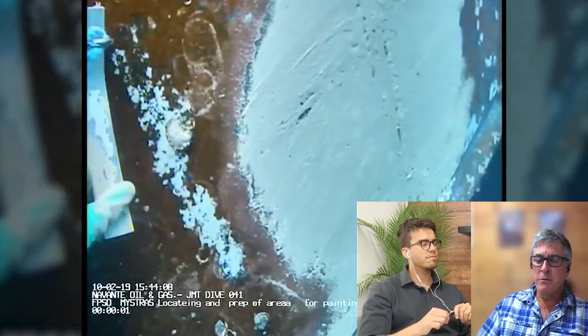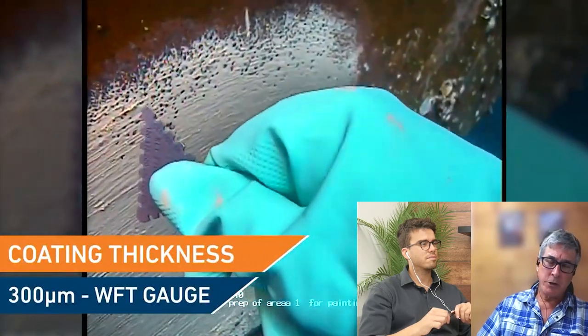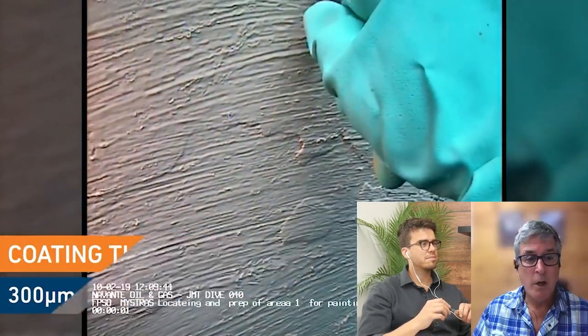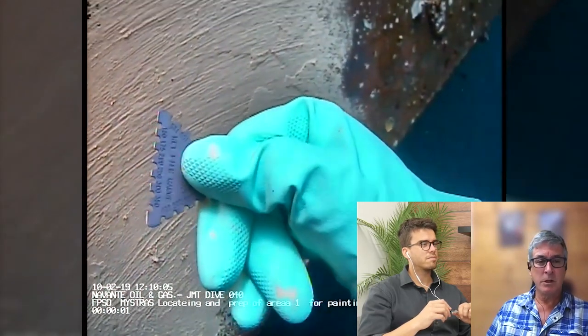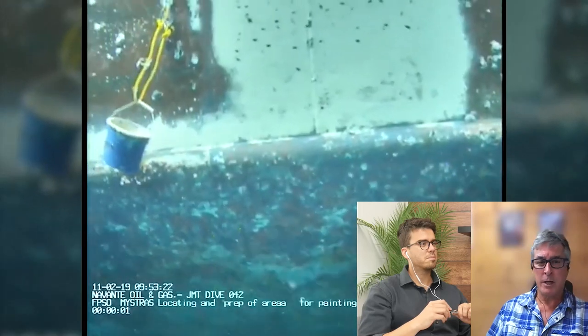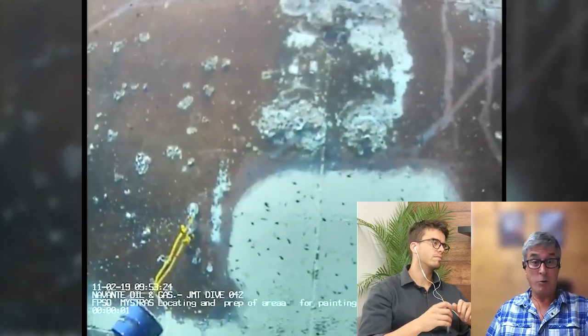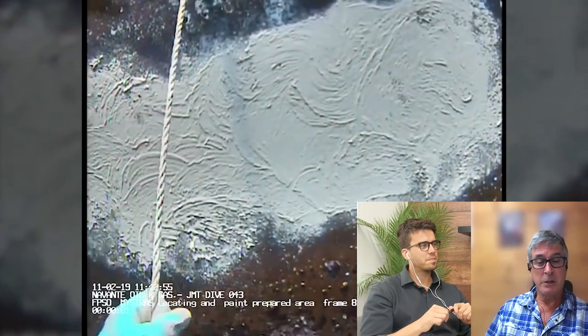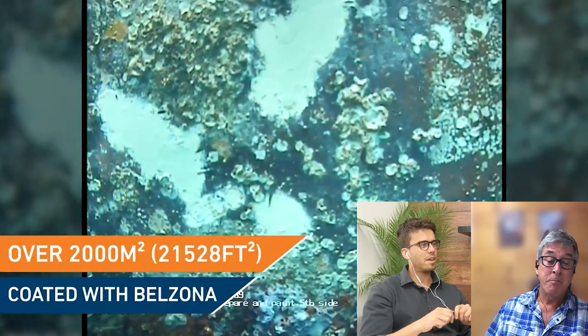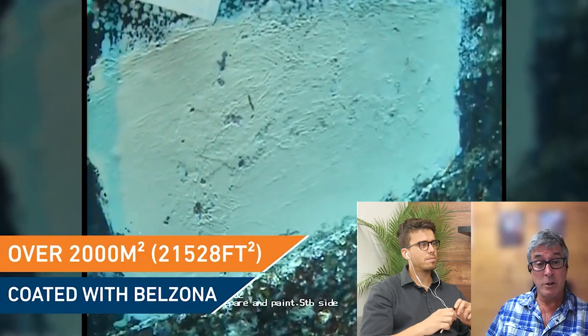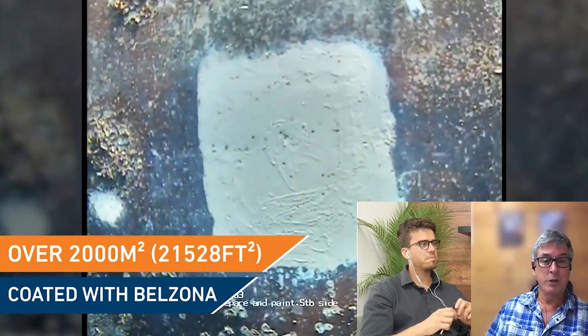In terms of value, often we're painting large areas. It's not all corrosion. We're painting large areas simply because the existing coatings are delaminating. The antifouls come off. We've lost coat 3 on an international product. Not all these coats are put on properly when they're painted on ships in foreign ports. So we prepare the areas where we have corrosion. We remove all loose coatings down to something which just isn't going to come off with a great deal of effort. And that's where you leave it, because you don't want to take off paint that's stuck onto the side of the shell plate properly.